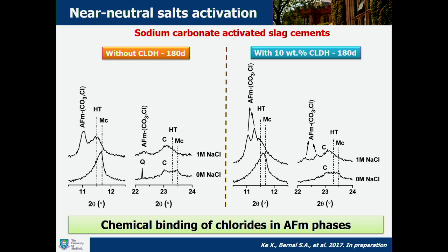But then we ask, will this be durable? Many of you that work with me know that I get carried away and I just want to answer every single question. So we did some preliminary studies, immersing these samples for nearly 1 year in chloride solutions. These are just some of the results we collected, and we can see that the formation of AFm phases, even without the CLDH addition, is very beneficial because we can identify chloride binding.